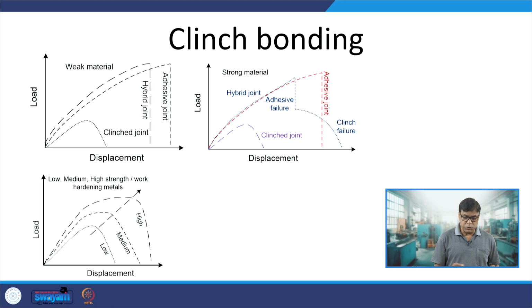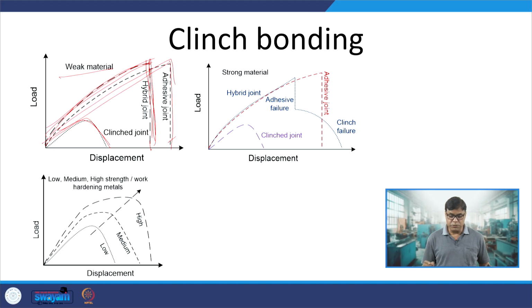So, what happens when we use a clinch joint of weak material? Okay, our load displacement curve is like this, where the load carrying capacity is very low and the displacement is also low. But when we use the hybrid joints, our load displacement curve becomes like this. So, only adhesive performs much better, but when combined with clinching, the load is almost the same, but the displacement is somewhat reduced.